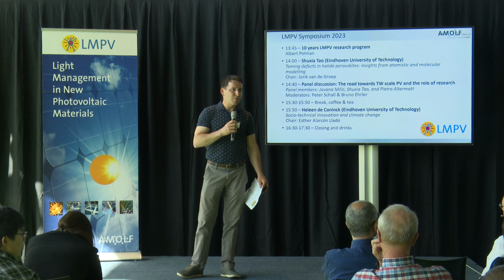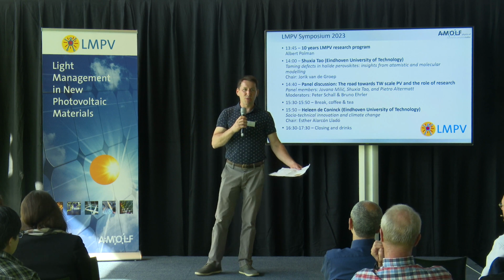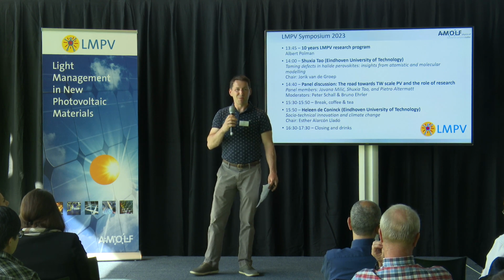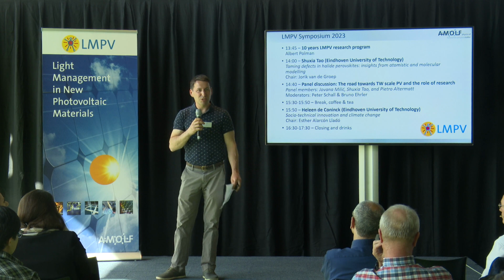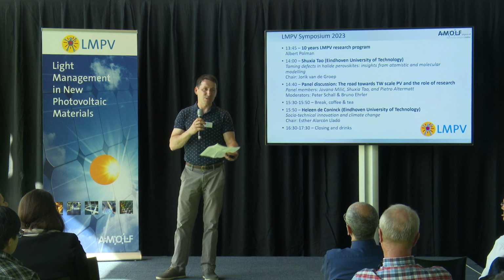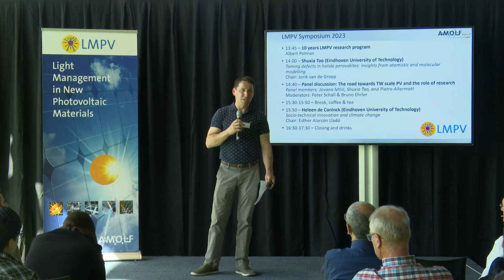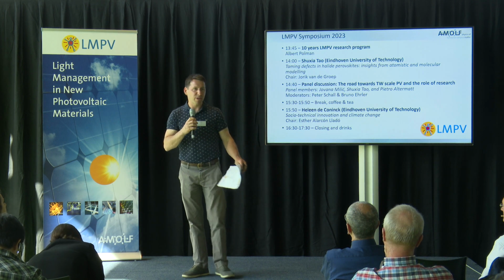And actually, I came first to know him at a conference, maybe it was 8 years ago or so in Germany, and he gave this plenary lecture where he was talking about all the things that you need to watch out for as an academic researcher to make sure that your research can be applicable in industrial PV. And in particular, at that time, something that people forgot to do is that they would try to make some nanophotonic structure for anti-reflection coating, let's say, and they would forget that in a real module you have encapsulation in glass, and that totally changes the properties of that coating. And so you can have an amazing coating on silicon-air, but then if you put it in a module, maybe it doesn't work as well as the industrial texture. And so he had a bunch of these little things like that, hey, just pay attention to this if you want to have more impact.